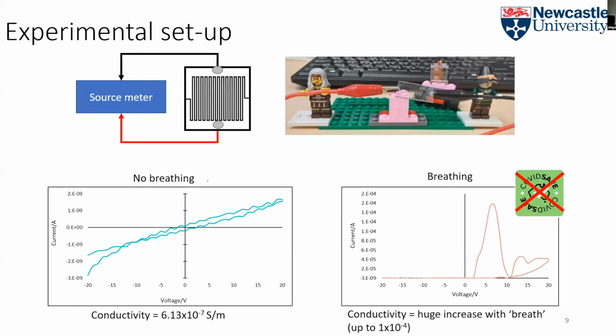So to go into the experimental setup, it started off very much school play toy level, but it worked. Basically what I did was laser scribed conductive glass, so I had ITO, deposited a layer of POM on that, attached silver paste to each side where the POM was scratched off, connected these with crocodile clips to a source meter and measured the current and the voltage.